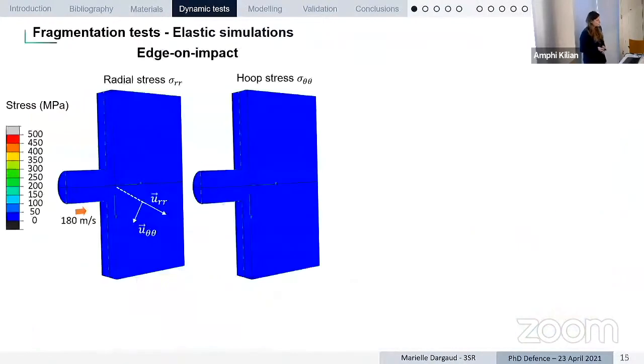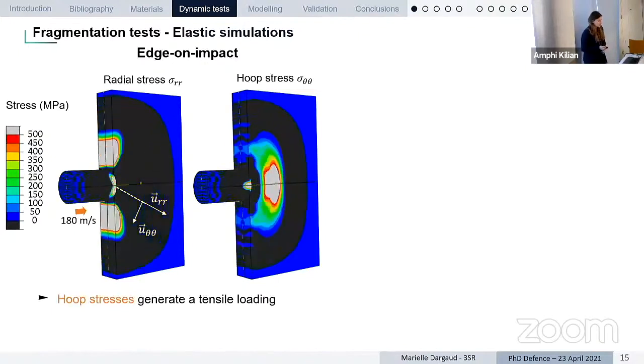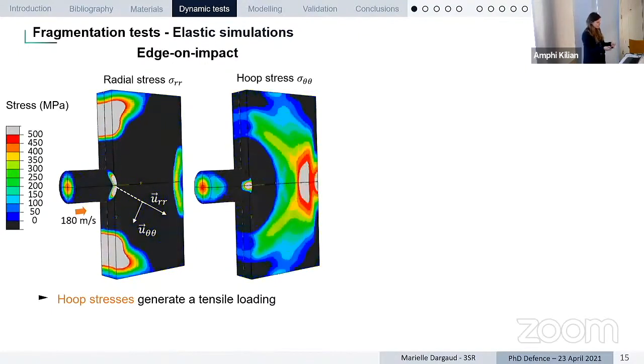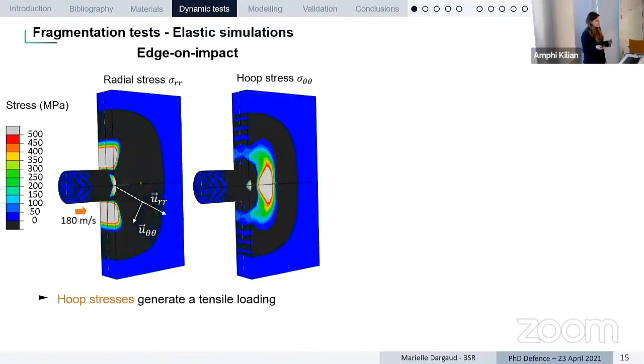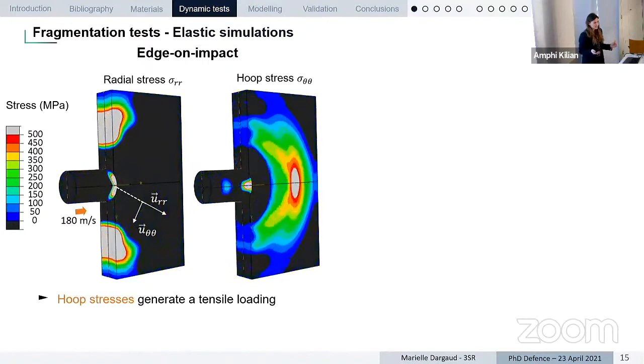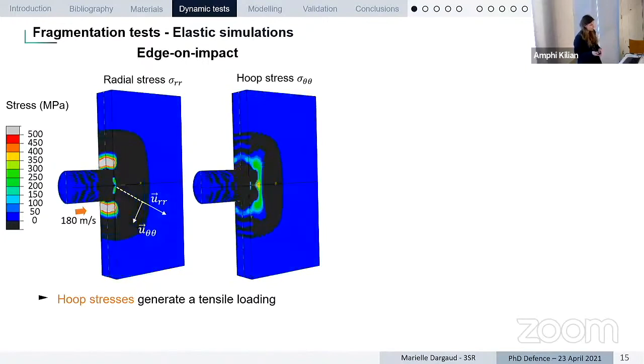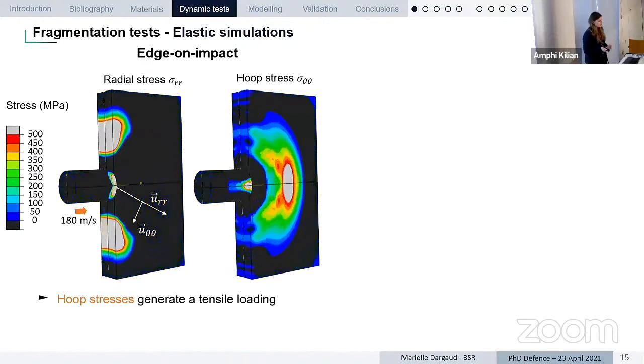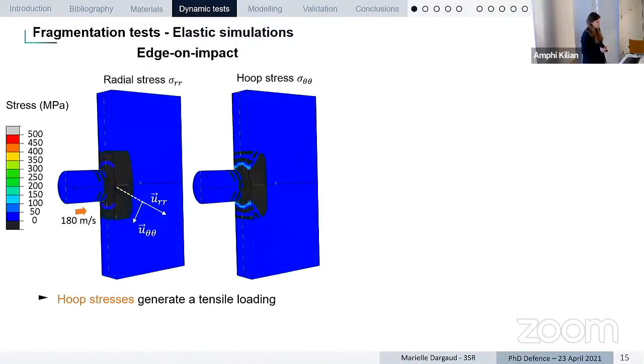First, we've performed fragmentation tests, which are the edge-on impact test. And here you have an elastic simulation showing the fields of stress propagating upon impact in the material, the radial stress and hoop stress. You can see that the impact generates a compressive loading, in dark here, which induces a tensile loading in the hoop stress along the loading axis. So here we managed to generate tensile loading in this configuration.